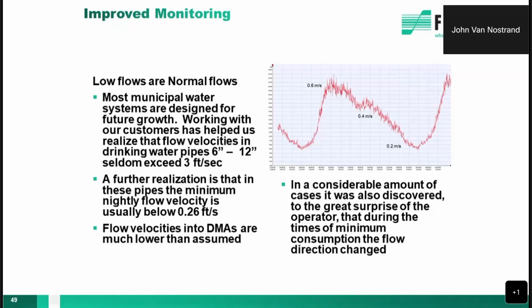And not all manufacturers are the same. Some are worse than others. And you'll get very low flows. And we see off-peak times the flow diminishes to velocities below 0.26 feet per second. Sometimes it even flows backwards. And with low flows like these, it's nearly impossible for conventional meters to capture the movement of the water.